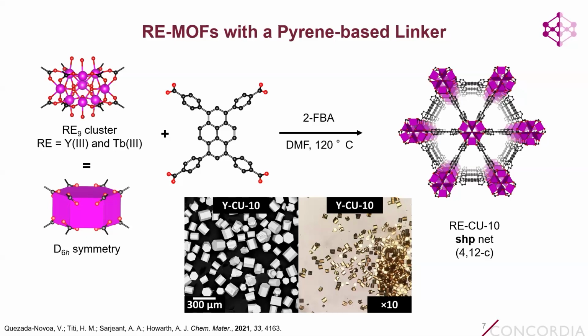And what was interesting is that the nonanuclear cluster node of this MOF is actually disordered over 2 positions. So at first we thought maybe it was a rare earth 18 cluster node, but actually it's the nonanuclear cluster over 2 different positions. And Victor was first able to make this with yttrium and terbium, and that node gives this double 6-membered ring building unit that's needed to make the SHP topology.